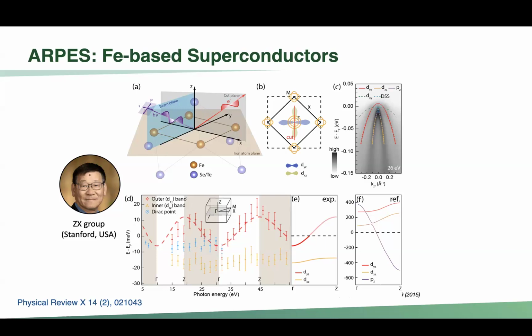A very interesting thing that was very helpful for us is the orbital content of the band, because like this, we can do group theory analysis and identify better the symmetries that determine the symmetry of the gap. What they told us is that we have two contributions, the dxz and dyz orbitals, and that we only needed to take these two into account.